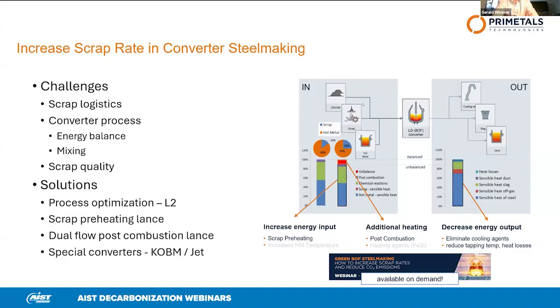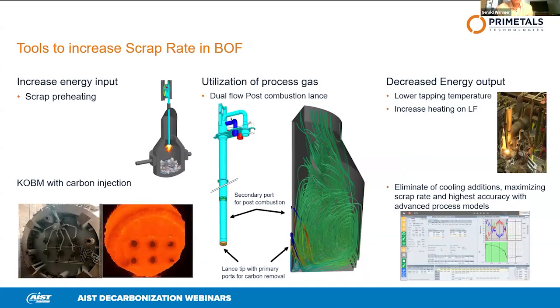And some examples of these tools to increase the energy supply and therefore the scrap rate we can see on the next slide. We can see some of these levers here on the very right-hand side, the scrap preheating lever, where we can preheat the scrap before we charge the metal. Such a system, for example, is used by voestalpine Donawitz. They have two small blast furnaces. When one of them is in relining or maintenance, they are short in hot metal and have excess time on their converters. So that's a good trick to use this time for scrap preheating.